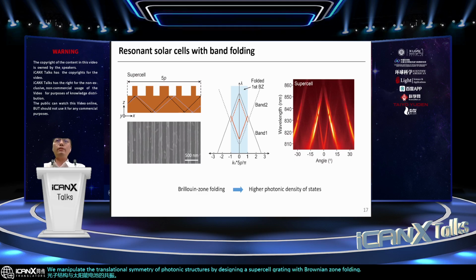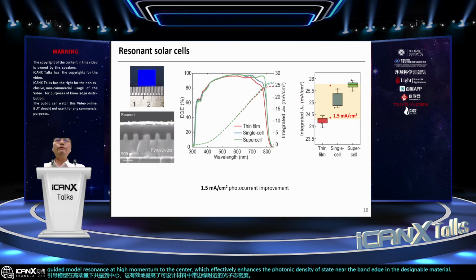This method folds guided mode resonances at high momentum to the Brillouin zone center, which effectively enhances the photonic density of states near the band edge in a designable manner. We then fabricate photonic structures onto perovskite over a large area. Notably, we observe a substantial increase in light absorption near the band edge.